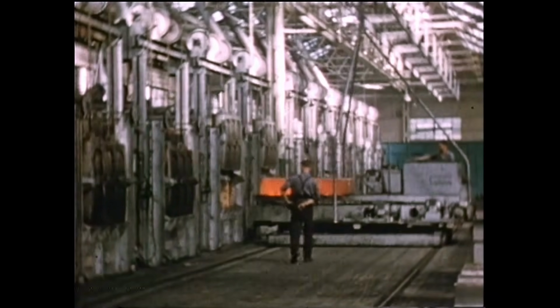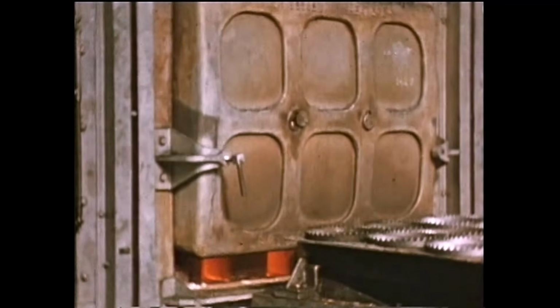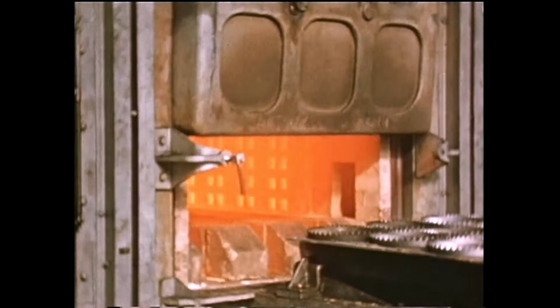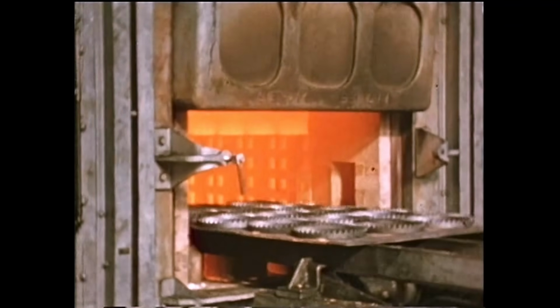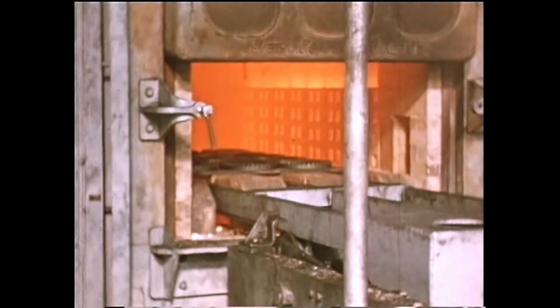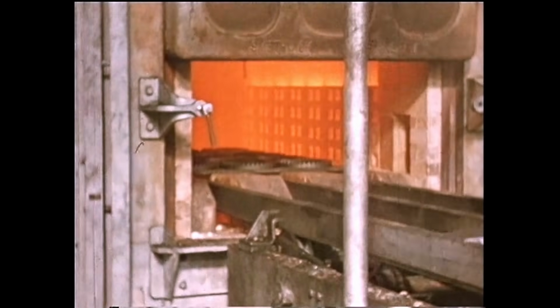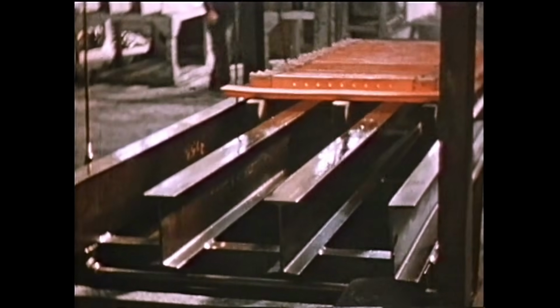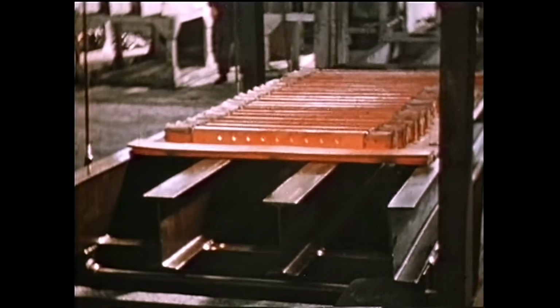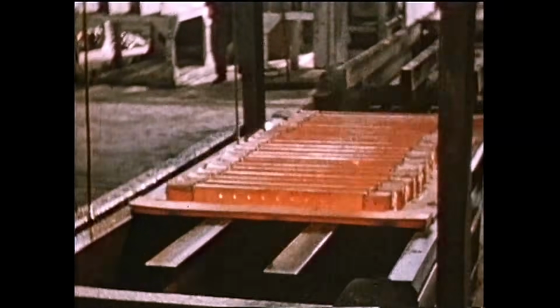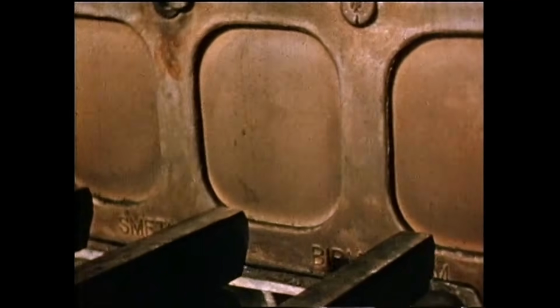The parts are now placed on open trays and fed again into the furnace for refining. This time they will remain for 30 minutes at 875 degrees centigrade. The mechanical loader is transporting a batch of drawbars to the oil quenching tanks, where they're quickly submerged in mineral oil. This causes the parts to cool fairly rapidly, thereby hardening and refining the steel. It also toughens the texture, which increases its resistance to withstand shocks.